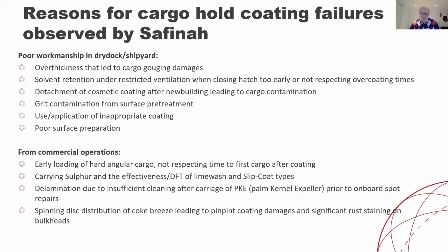Detachment of cosmetic coatings, which I already mentioned, leading then to cargo contamination. It could be grit from surface pretreatment, actually using the inappropriate coating for your purpose and your operating conditions, or poor surface protection, poor surface preparation. From commercial operations, we see failures like failures from early loading of hard angular cargoes like coal, carrying sulfur, and the effectiveness of various lime wash or slip coat types, delamination due to insufficient cleaning before you do spot repairs, or it could be the way you are loading, like for instance spinning disc distribution or coke breeze, making a lot of pinpoint damages and rust staining in the bulkheads.